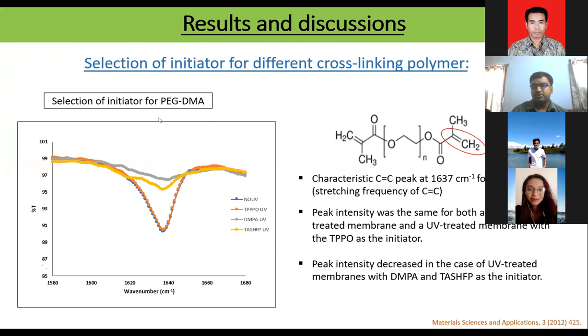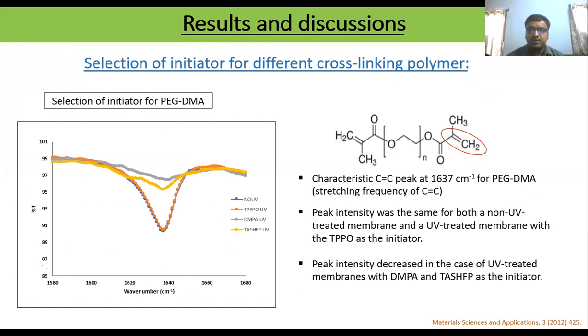So first, when we prepared the membrane, we had to select the best initiator. As I mentioned earlier, we have used three different initiators. So for each base polymer, our first target was to find an optimum initiator which worked better for that particular cross-linking polymer. So in this study, this is the double bond that is present in the cross-linking agent. So what happened when you do the cross-linking? This bond breaks and it forms a new bond with the next cross-linking agent.